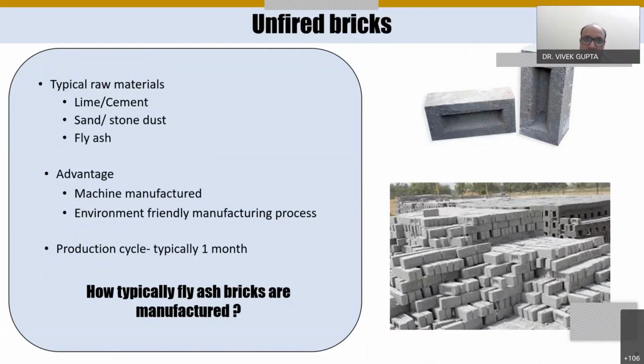Then what are the advantages of the unfired bricks as compared to the fired bricks? These are machine manufactured bricks, and the manufacturing process is environment friendly, and the typical production cycle is 1 month. However, it depends on the weather conditions. Whenever we have the winter season, the curing cycle becomes a little bit longer, and whenever we have the summer season, the brick curing becomes faster. There are no specific research studies reported, but I have previous experience in the industry, so by experience I can say it depends on the weather conditions. The rate of strengthening of the bricks is closely related to the conditions in the weather.